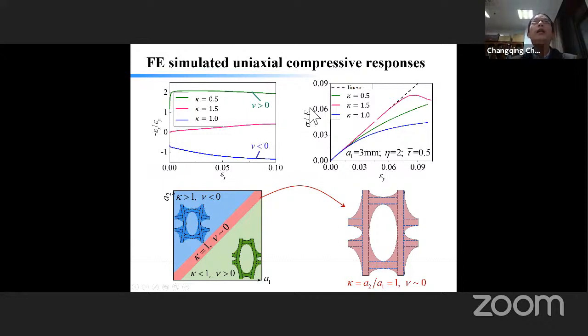If we look at the normalized stress as a function of strain, you will see that for kappa not equal to one, we have a monotonic increase of the stress as the strain increases. However, for kappa about one, you will see a peak here. Now we can plot a phase diagram in terms of A1 and A2. Remember, kappa is defined as the ratio between A2 and A1. For kappa greater than one, we have negative Poisson's ratio, and for kappa less than one, we have positive Poisson's ratio. What is most interesting is this one: kappa about one, the red line here, where the Poisson's ratio is close to zero.